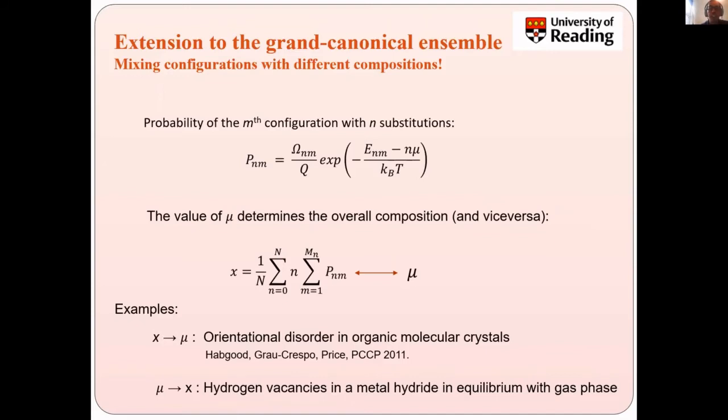One of the first lessons that you learn when you start doing computational chemistry is that you shouldn't mix energies. You couldn't compare energies of systems that have different compositions. You wouldn't dare to do that. Your professor would tell you off. But there is a very important trick to learn, which is using chemical potentials. With chemical potentials, you can always compare things that have different compositions, because you say, okay, whatever is not in the system is somewhere else with a chemical potential mu, and then I introduce it as a variable. And that allows you to couple calculations that you do in a solid, for example, with an external phase.